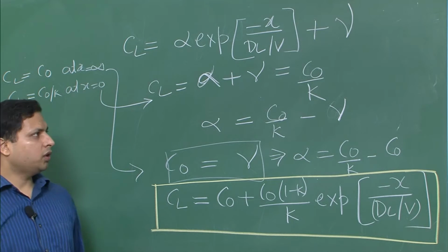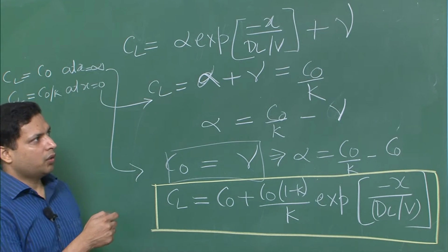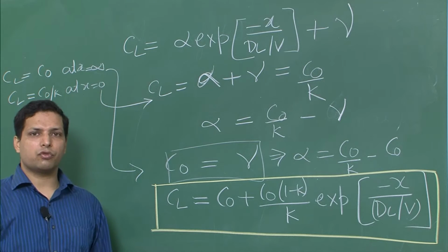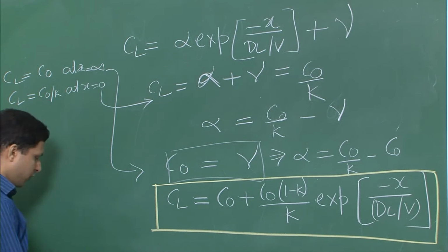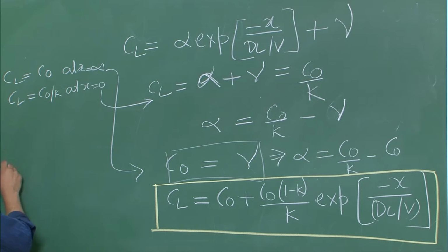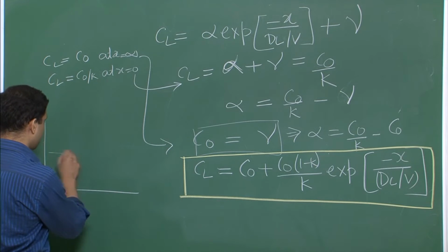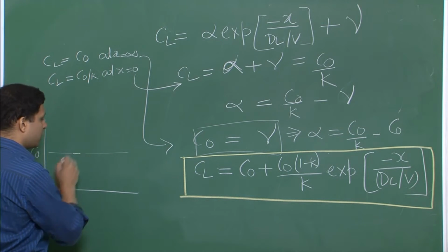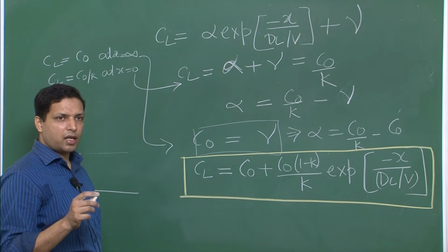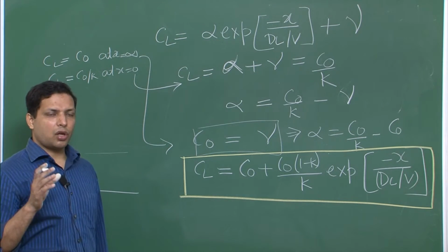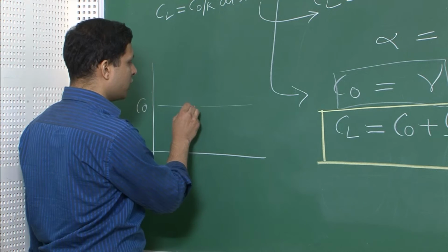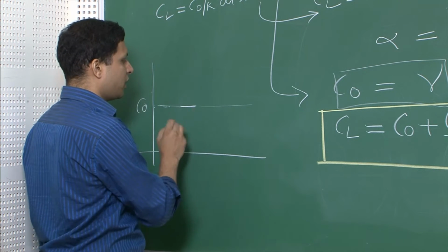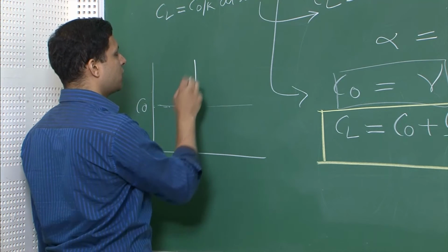So, for the condition of no solid diffusion with limited liquid diffusion and in the steady state, we have obtained the concentration profile of the liquid. Let us again draw this plot. We had this C naught and somewhere the solid is forming, and since it is in the steady state, the crystal is so long that the solid concentration is also equal to C naught. So, this is the concentration of solid over here. Over here we do not know, it is the transient state. Somewhere over here it has reached steady state, and at this point this is the concentration of liquid.